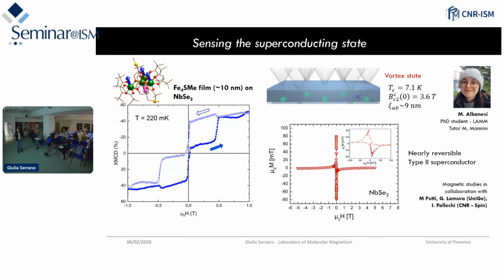Then we also measured the magnetization of the niobium diselenide without molecules, to know that this niobium diselenide has a reversible hysteresis loop, that if you look at what is happening at very low field, has a strange opening of the hysteresis loop that we are going to comment on when we see the hysteresis of the molecules close to zero.